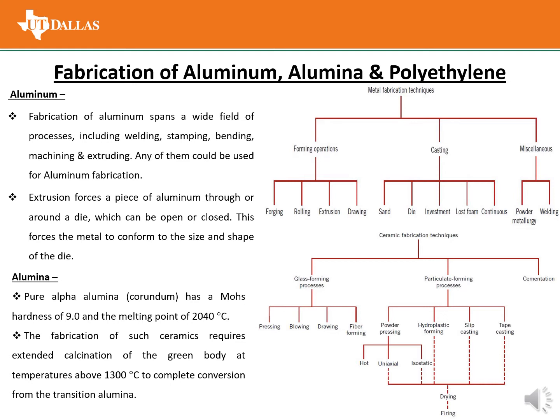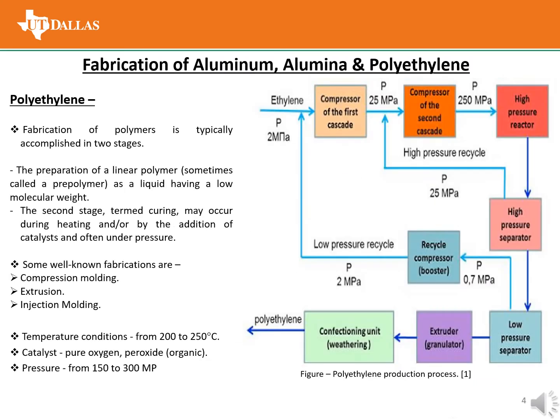And then alumina. Alumina is a ceramic, so alumina can also be fabricated using different techniques. From Callister's book we know there are glass forming processes, particulate forming processes, and cementation, and they all consist of several processes. Pure alpha alumina's melting point is 2040 degrees Celsius. For that reason, the fabrication of such ceramic requires extended calcination of the green body, and the temperature should be above 1300 degrees Celsius. It's time to talk about polyethylene fabrication.